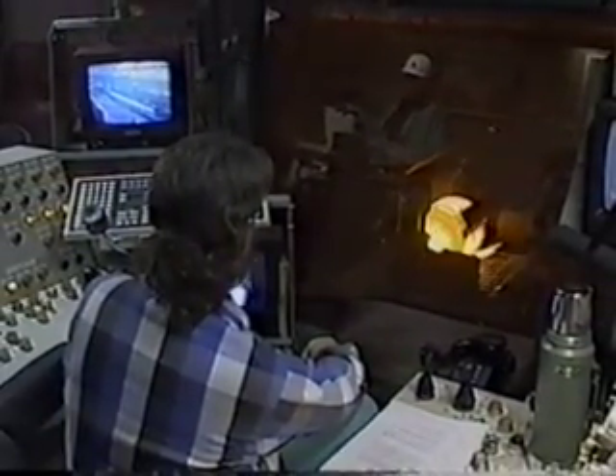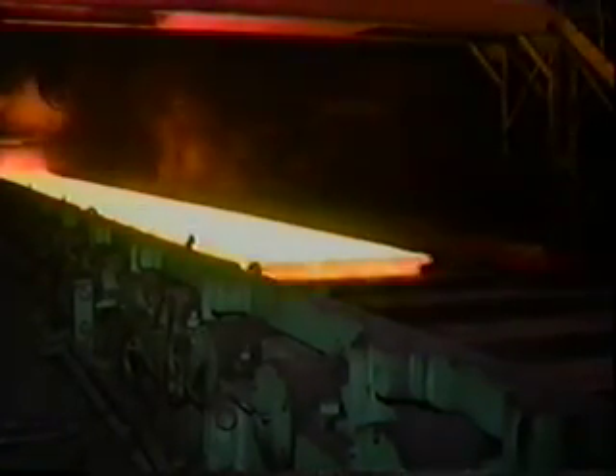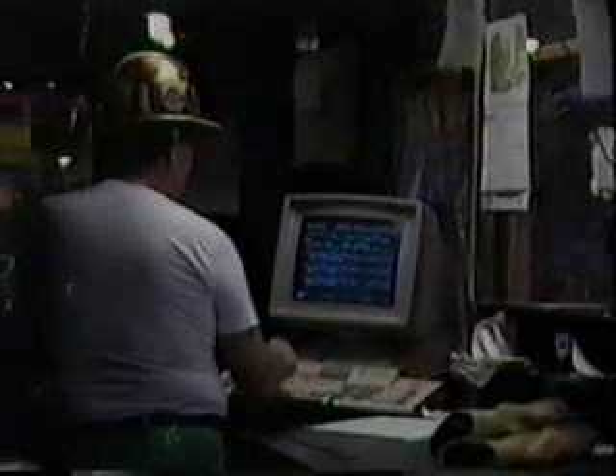A hot strip coil box processes this 2,000-degree, 1-inch thick transfer bar into a coil form for temperature conservation and equalization. Next, the steel is uncoiled to the finishing mill at an even temperature profile, which helps achieve the temperature and thickness control needed for the customer's order. The coil box helps conserve the reheat furnace fuels and the electrical power requirement.